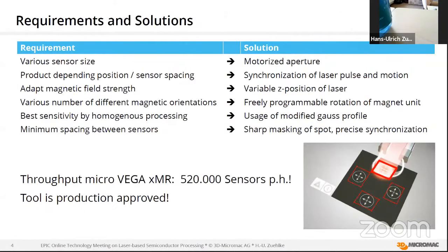So we had several requirements and challenges before we designed this tool. We have many different sizes of the sensor. So we have to use a motorized aperture to adapt the laser spot. The basic idea is on the lower right corner, you have the different sensor areas. You apply a magnetic field, and one sensor you heat up by laser with one laser pulse. And then you fix the orientation of the magnetic field. You remove the laser and the magnet, and the orientation will be stable. And then you rotate the magnet unit, and you get all the required magnets in the Wheatstone bridge.